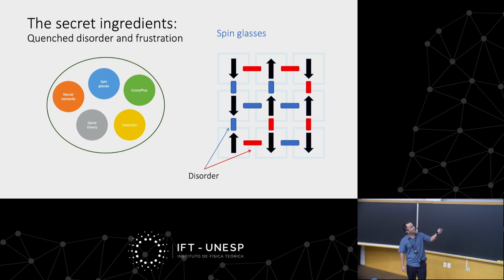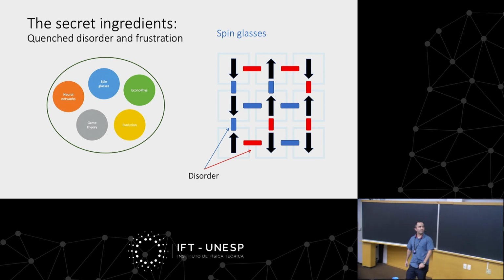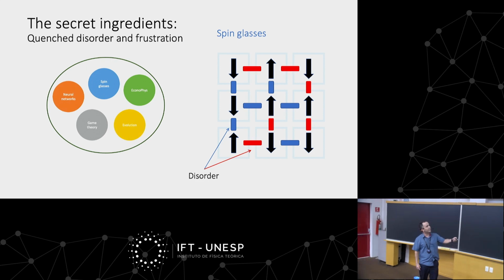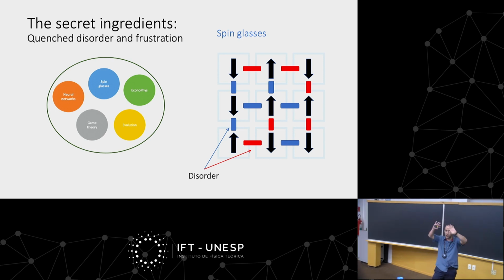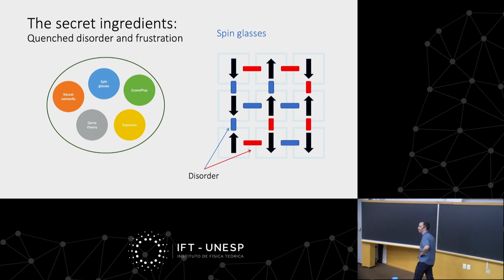And then they interact so that if this is blue, for instance, they like to be parallel, pointing in the same direction. And if those are red, they like to be anti-parallel. So there is competition between ferromagnetic and anti-ferromagnetic interactions. So this, in principle, for a spin glass is disordered. There is a random variable associated with those interactions. And this gives rise to this spin glass phase where the spins are frozen, but in some disordered configuration.